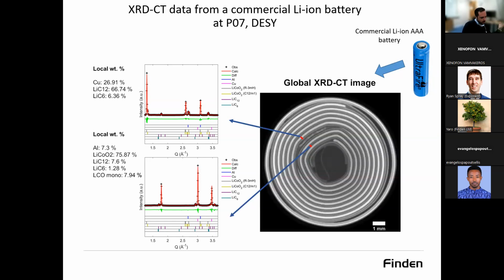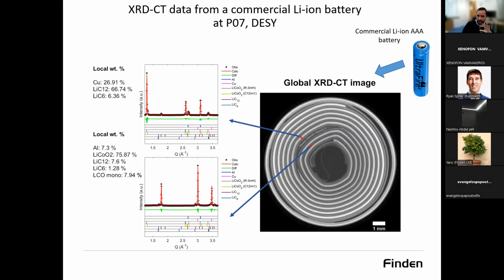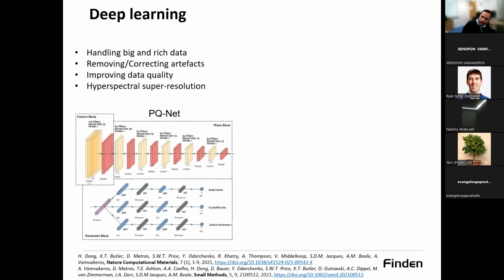So that means that very often conventional data analysis software packages, open source or commercial, it doesn't matter, they fail. They are not robust enough that you can have one starting model and say to the program, go and analyze all these local diffraction patterns or local spectra or whatever you wish. So very often they can crash. And this was one of the main reasons that we spent a lot of effort at Finden developing state-of-the-art AI approaches to handle these large and chemically rich datasets.